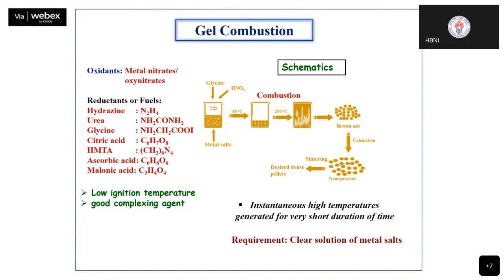Once I do, now the fuel, which has got nitrate with it in the solution, has reached its ignition temperature. So it will burn. Okay. Externally, I have applied only 250 or 300. But internally, when combustion happens for a few seconds, a very high temperature of the order of 1200, 1400, depending on the amount of fuel, amount of oxidant, ratio of fuel and oxidant, will be reached. Okay. And because of that high temperature generated for a very short interval of time in my beaker, my reaction proceeds.